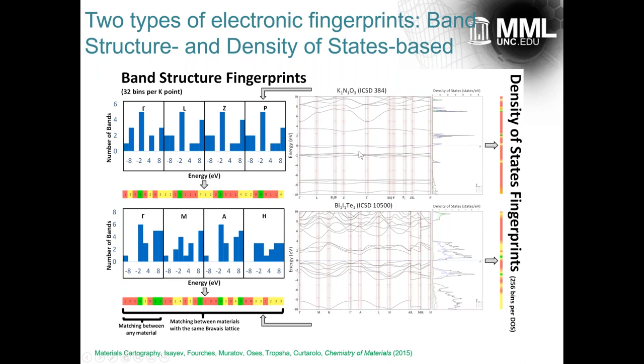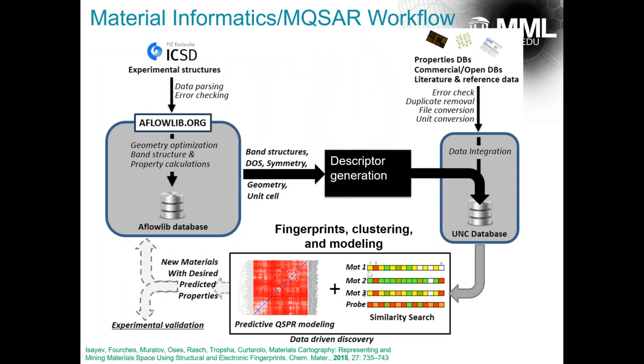This diagram comes out of conventional DFT level calculations of the structure of these materials, in the form of an electronic band diagram on the right, and we transform this into molecular fingerprints. For each material, each of these band diagrams is transformed, which we describe carefully in the paper, so I won't go into any detail, into band structure fingerprints, where different levels of these diagrams are represented by energy levels and by numerical groups. This transformation then allows us to represent each material by its fingerprint, a concept completely borrowed from cheminformatics.